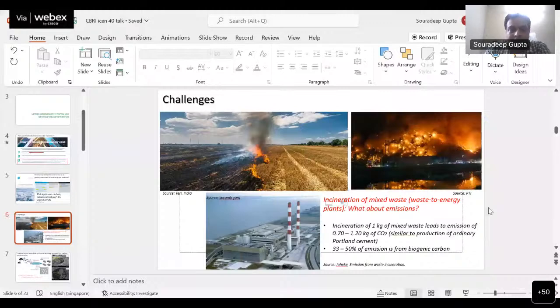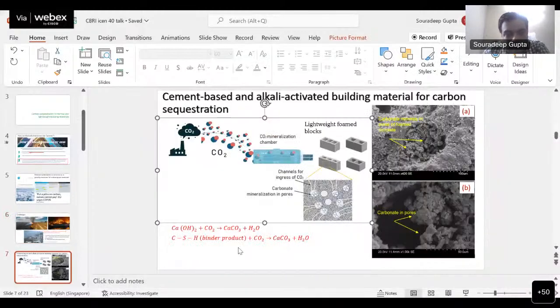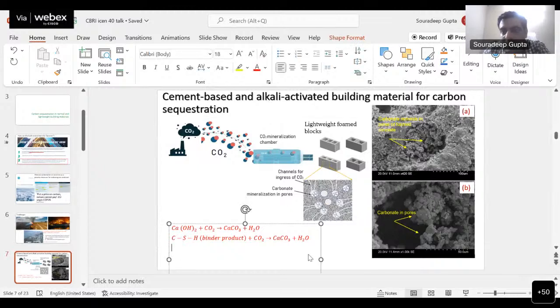And through diffusion, let me turn on the pointer. And through diffusion, the CO2 can enter the matrix, react with the hydration products, for example, calcium hydroxide and calcium silicate hydrate, and get deposited in the pores as carbonate minerals. And here are some scanning electron micrograph photos we have taken last year using CO2 capturing technology in lightweight concrete. And you can see this kind of depositions inside the pores of lightweight foam concrete. These are basically the mineral carbonates that have been formed due to reaction of CO2 with the hydration product.